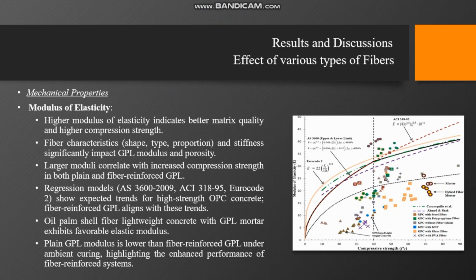Fiber type, shape, and proportion influence the performance, affecting both the geopolymer modulus and matrix porosity. The larger moduli in plain and fiber-reinforced geopolymer correlate with increased compression strength. The figure compares the regression models for high strength concrete with elastic modulus data for plain and fiber-reinforced geopolymer. The fiber-reinforced geopolymer shows trends similar to Portland cement with convergence in compression strength. The oil palm shell fiber lightweight concrete with geopolymer mortar compares favorably due to the concrete's heterogeneous nature. Notably, the plain geopolymer modulus remains lower than the fiber-reinforced geopolymer systems under ambient curing, showcasing their distinct performance characteristics.